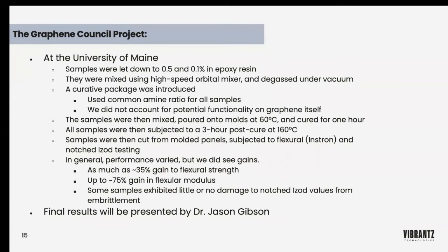We used a common amine ratio stoichiometry of amine to resin for all samples. We did not account for a variation in the functionality of the graphene itself because this was a blind study. The samples were then mixed, poured onto molds at 60 degrees Celsius, cured for 1 hour, and then subjected to a 3-hour post-cure at 160. After that, they were cut from molded panels and subjected to flexural and notched izod testing.